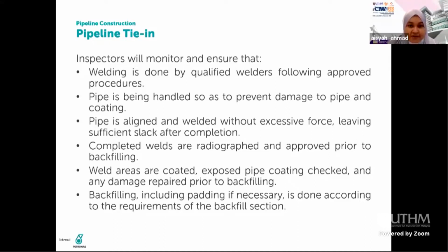Pipe is aligned and welded without excessive force, meaning that sometimes when we put the pipeline inside the trench, we cannot align it together, sometimes due to an obstacle at site or maybe due to the terrain itself. We need to ensure that the pipeline is aligned. So that's where the challenges usually are when we are constructing the pipeline.